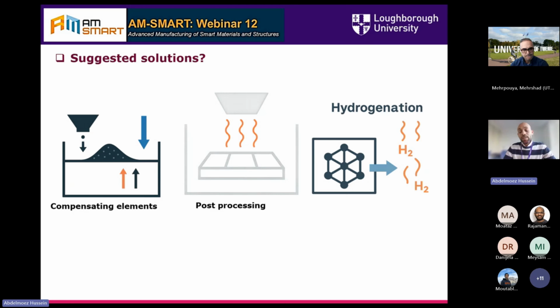The hydrogenation, which is heat treatment in hydrogen atmosphere, is also important for some of the materials because it can break down or decompose the oxides that have been formed during the process itself. So this is very critical. Both alloys and both examples that I have used today have been hydrogenated, have been heat treated in hydrogen atmosphere with a specific pressure as well.